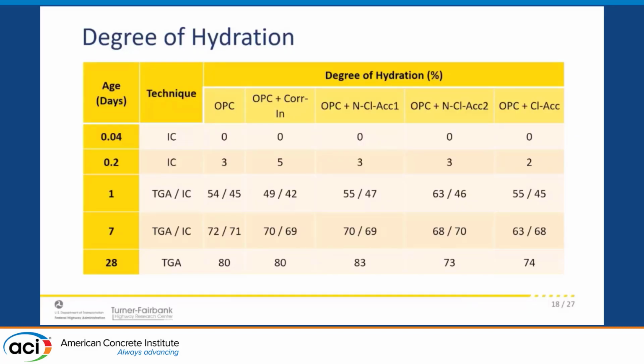So these are the results on the degree of hydration. As I mentioned, for the early ages, we relied on isothermal calorimetry, and for the later ages, we relied instead on TGA. You can see there's a little bit of discrepancy at 1 day between TGA and isothermal calorimetry. Typically, TGA is not very recommended for such early ages, so that's why we relied on isothermal calorimetry for those. These testing ages match the ages at which we tested the pore solution and the bulk resistivity.